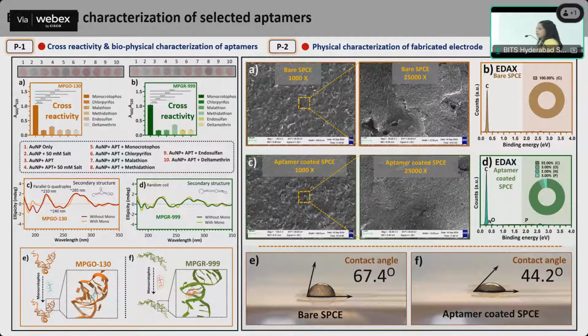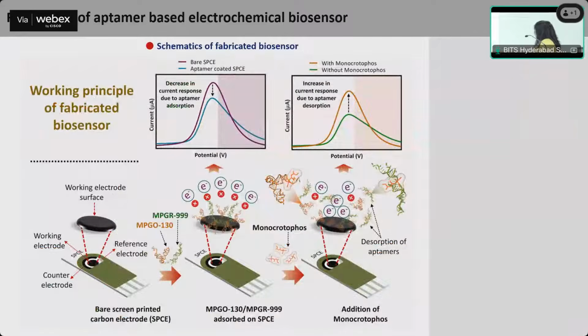So here we have utilized the SPCE electrodes. You can see this is the SEM morphology of the bare electrodes, and this is the magnified image. After aptamer coating, you can see there is a change in the morphology, and EDX analysis also confirmed the presence of the aptamers, which was not there in case of bare SPCE. Later, the contact angle was also analyzed. In this case, it shows that aptamers are bound, and there is a change in the hydrophilic nature of the electrode, which says that the aptamers are bound efficiently onto the electrode surface. So this is the scheme which tells us how we have done the fabrication of these two electrodes with the two different aptamers.